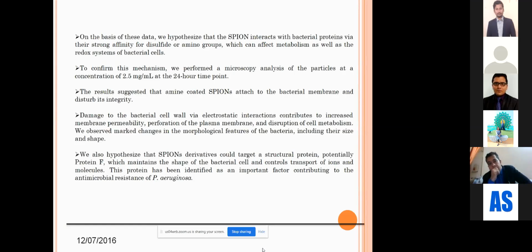Damage to the bacterial cell via electrostatic interaction contributes to increased membrane permeability, perforation of the plasma membrane, and disruption of the cell metabolism. We observed marked changes in the morphological features of the bacteria, in the size and the surface, and how it got modified. So we hypothesize that the SPION derivative could target a structural protein, potentially protein F, which maintains the shape of the bacterial cell and controls the transport of ions and molecules. This protein has been identified as an important factor contributing to antimicrobial resistance, particularly in Pseudomonas aeruginosa.